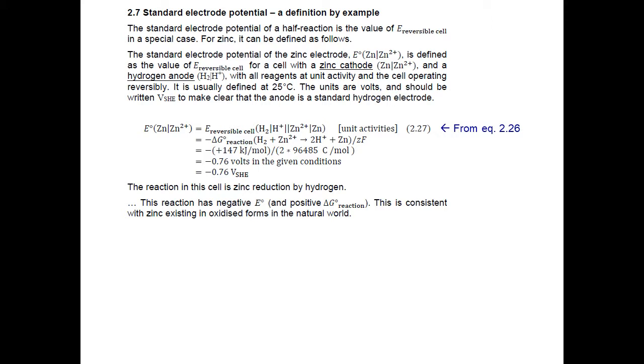So for zinc, standard electrode potential can be defined as follows. It's the value of this reversible cell potential in a special case. The standard electrode potential of the zinc electrode, denoted in algebra by E superscript circle and then brackets around the zinc electrode notation, is defined as the value of the reversible cell potential difference if we have set up a cell with a zinc cathode, that means zinc ions are plated to zinc metal, and a hydrogen anode. And in this cell all the reagents are at unit activity and the cell is operating reversibly. That means fairly slowly.